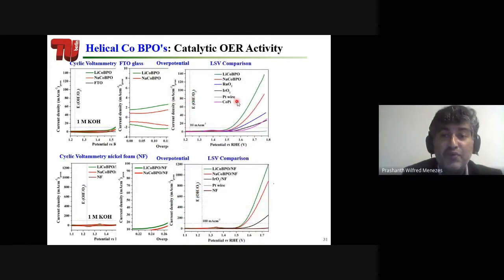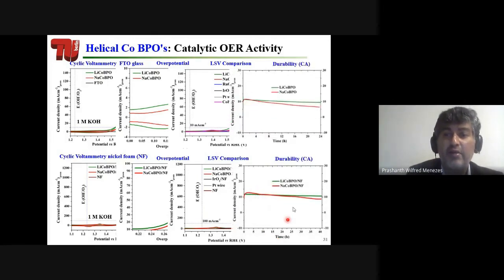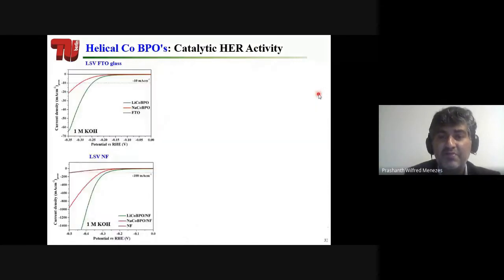And this overpotential, what we show, is much better than the ones which we tested for noble metals, which I already showed you in the volcano plot, that all the noble metals are very good for oxygen evolution reaction. But we show that a cheap metal also can be used and could be implemented in electrolyzers. And as the stability is one of the important factor, we also test the stability exactly at this 10 milliamp current, and we show that they are very stable at least for 40 hours.